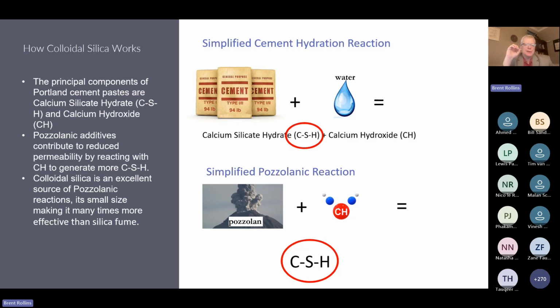Among other reaction products, there's one called calcium hydroxide that is also produced. That calcium hydroxide really doesn't add much to strength or durability. It just sort of sits around in the concrete waiting on something to react. Well, along comes pozzolan. If we put pozzolan in the concrete, whether it's mixed in or somehow applied later, as we'll see, you get a chemical reaction that consumes some of that calcium hydroxide or portlandite to produce, guess what? More CSH. That same reaction product that produces that strength and durability that we want with concrete. The pozzolan produces that secondary CSH. So that's the key reaction.